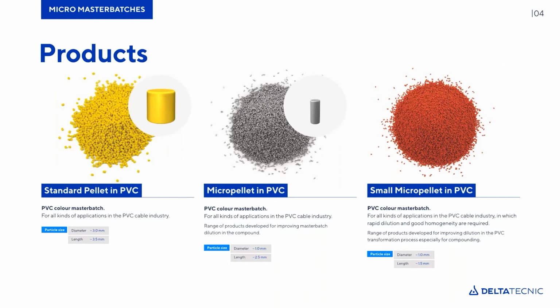That means that it is several times smaller in terms of mass than the standard pellet, and therefore it melts much quicker, and therefore it facilitates dilution. The melting process gets accelerated. And this happens even more with the small micro pellet, which is only 1 millimeter of diameter, same as the micro pellet, but the length is just 1.5 millimeters, so it's much shorter in terms of the length. So these are the 3 products that are destined for the cable manufacturing.